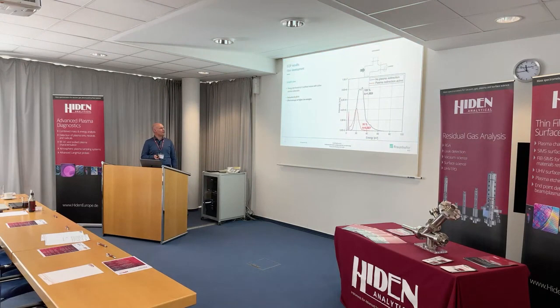So now let's come to the EQP results. To remember, this is our plasma source here, our base chamber, and this is the place where we are starting the measuring. And we did some no plasma redirection measurements in the beginning. And this is the graph of it here, with the energy in electron volts. This is always easily possible if it's single charged ions. Then you do not have to think about voltage or electron volts. The count rates are good, of course, and I put this to 100%.